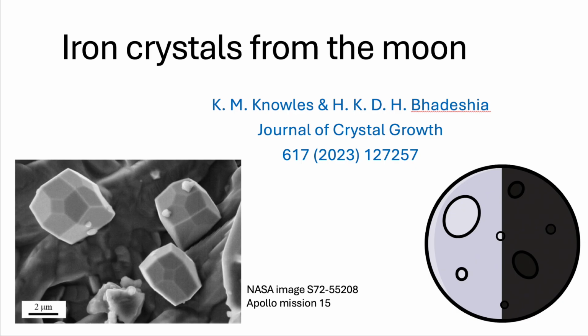And when you get these large unequal numbers like {hkl} where l is much bigger than h, well, that means the face is tilted, sometimes very steeply, relative to those main axes. And that creates these really complex, you might say, exotic geometries. Okay. And this created the big challenge, didn't it? Because these crystals are tiny. Microscopic, just a few micrometers across.